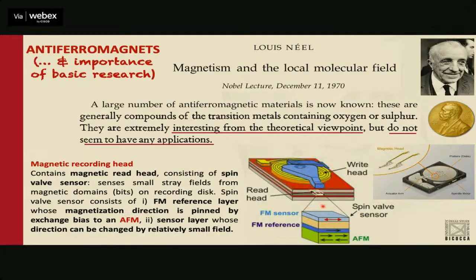And then this upper, let's say, ferromagnetic sensor just lines up with the local region in which you have a magnetization pointing left or right. And then depending on whether the two layers are lined up or anti-aligned, you have a certain different current. And so you basically need to have a free layer which just follows the direction of the magnetic bit that you're sensing, but this other one needs to be fixed. And the way you clamp it is through connection with an antiferromagnetic material, with a mechanism called exchange bias. So in every hard disk, you have an antiferromagnet.